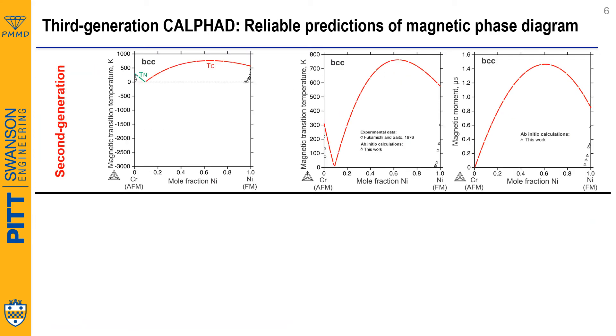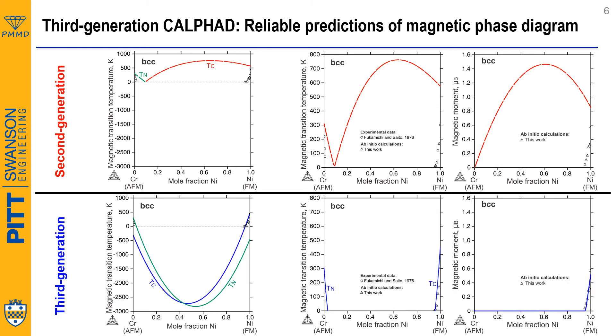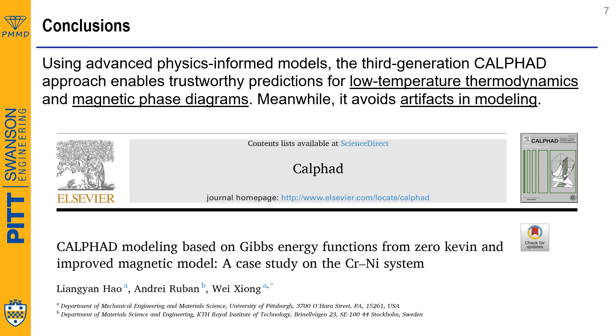Finally, the second generation CALPHAD uses a single equation to describe both Curie and Néel temperatures, while the third generation CALPHAD uses two polynomials to describe these temperatures separately. Therefore, both the antiferromagnetism on the chromium-rich side and ferromagnetism on the nickel-rich side are properly calculated. More importantly, no magnetism is introduced in the middle compositions.